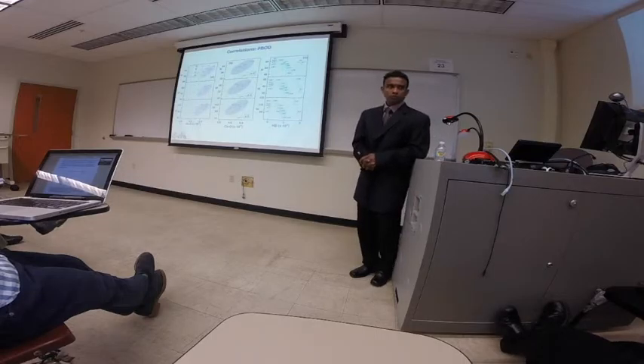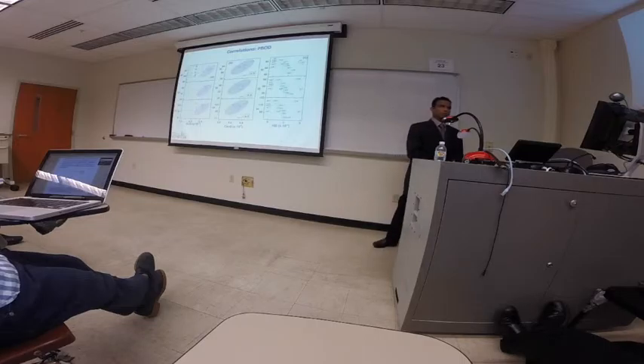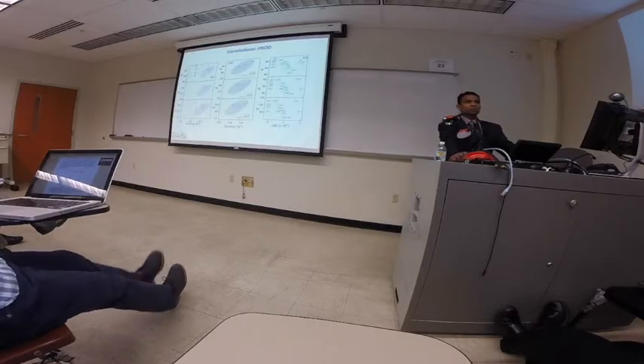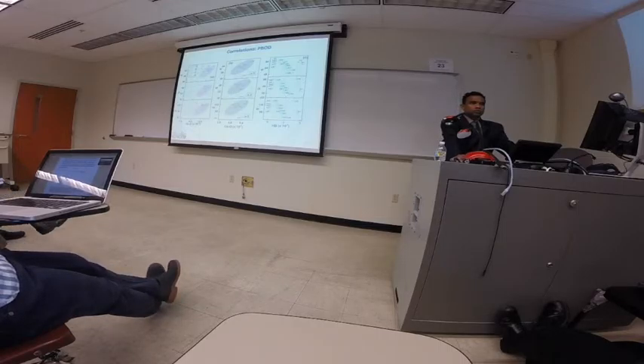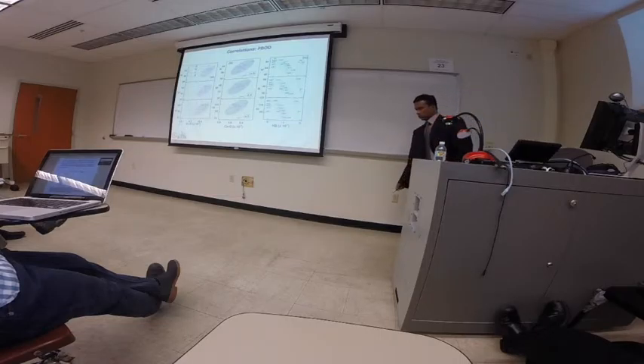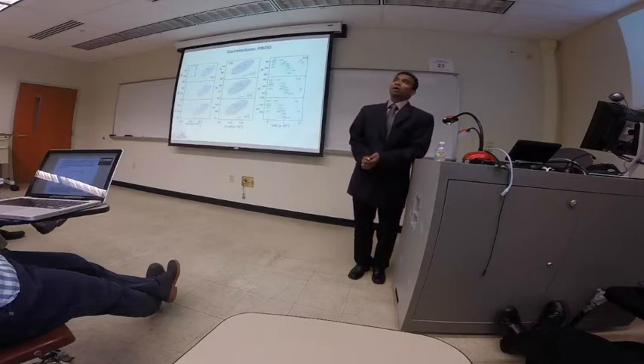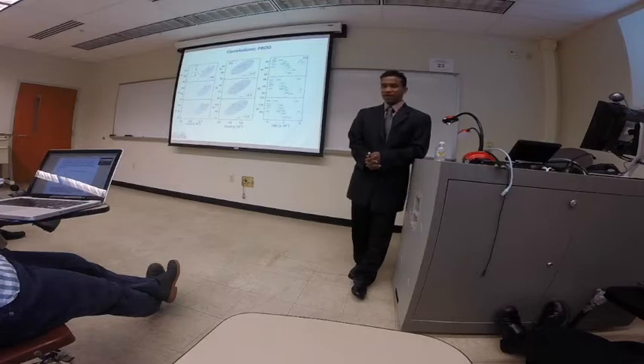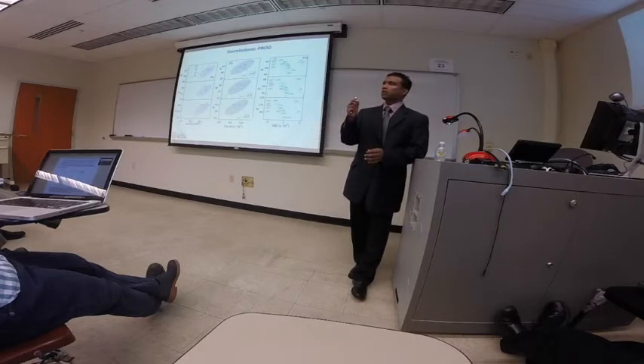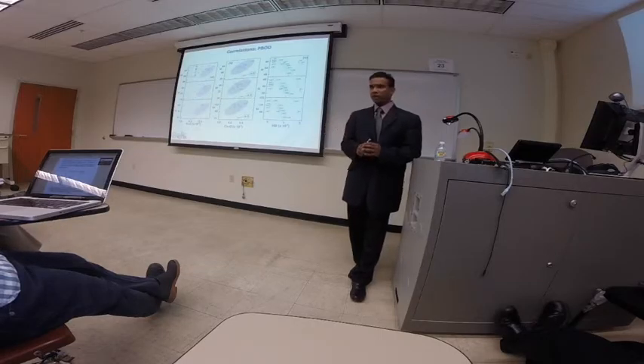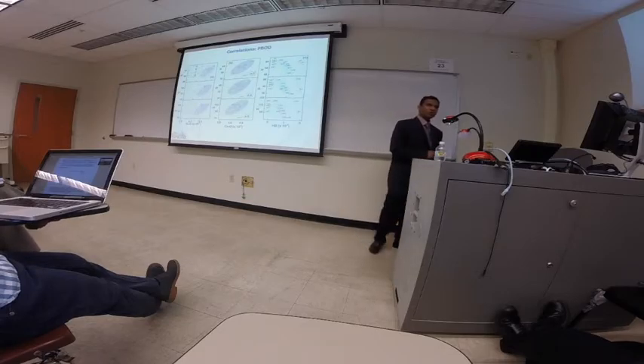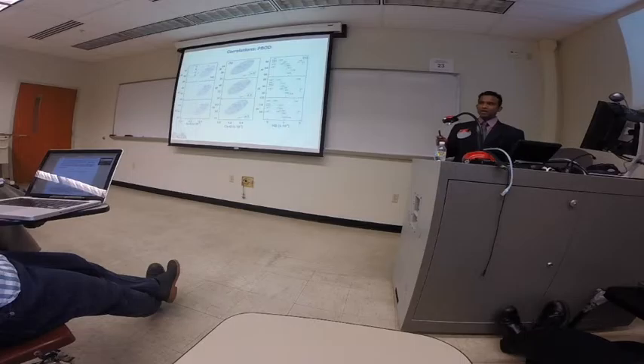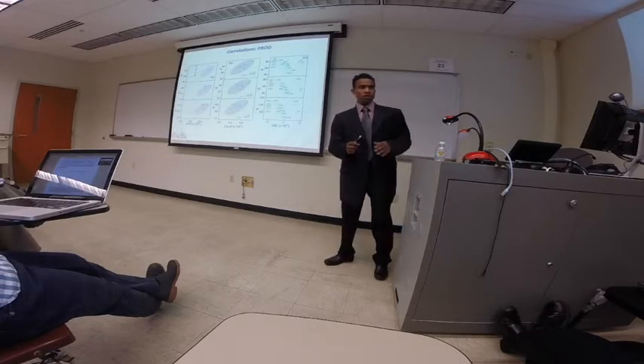Could you imagine some other way? Not that you're going to do it, not that you did, but if you wanted to try to dissect it in a different way, is there some other way that you could try to characterize the mechanical properties of the crystals, to understand the anisotropy a little bit better? The anisotropy of cement, we didn't include. We have done the study because there's a universal anisotropic parameter defined for very inhomogeneous crystals, and we played with this, and we found, although the crystal structure is very different, mechanically cement is not that anisotropic at all. The bulk cement.